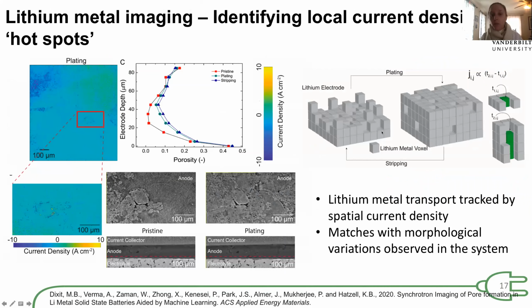We ran our 3D tomography experiments. We have gone through each of these images and looked at tracking the ionic flux at this interface. This is the lithium metal interface, and the blue region is low flux and the yellow region is high flux. One thing I want to bring to everyone's attention is we're making the move toward quantification of these images, but what we try to emphasize is that the magnitude is not necessarily the most impactful quantity, but a trend is a much more reliable observation.